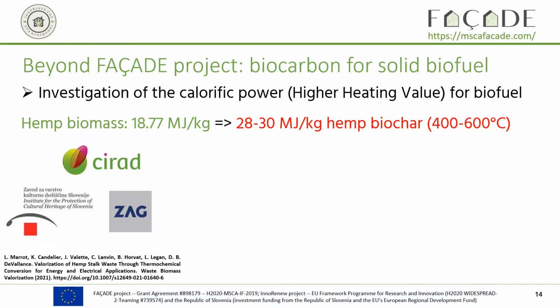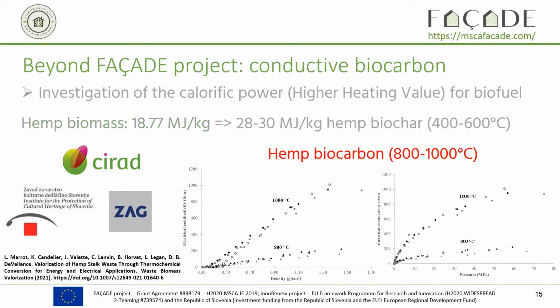And the higher the carbonization temperature, the more you increase the calorific power, up to a temperature from 400 to 600 degrees. When we went to higher temperatures, we got a stabilization of the calorific power, and we did not manage to increase it, and the yield was, on the contrary, decreasing. So we recommended to use the hemp biochar for solid biofuel application only at 400 to 600 degrees.